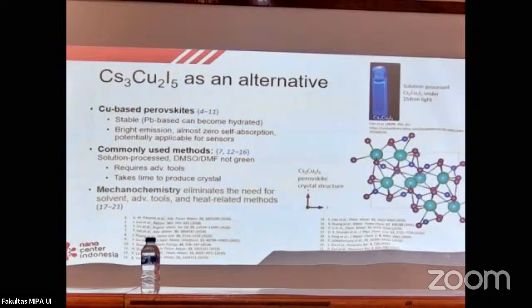So we have interest in using this class of material because in the past, copper-based perovskites have been known to compete as a competitor for the lead-based ones that have become annoying due to toxicity. And now the reason why we choose another way to obtain the perovskite is using mechanochemistry. Mechanochemical is basically a simplified method that I will show you in the next slide. So we use this class of perovskite structure because in the past the system is already quite developed.